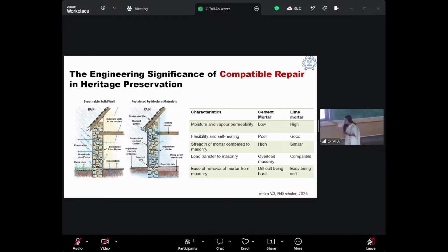When you are sealing it with a cement plaster now to make it repaired or to make it new, you are sealing all this water, vapor movement, salt, everything inside. So pressure starts building up. Crystals will grow, it will exert stress. What happens when stress builds up inside? It bursts one day. In structures, it doesn't burst like us, but when pressure builds up, cracks form in those portions and cracks extend and then failure happens. And that new layer that you added will come out along with some of the heritage material, which is stone. This is why cement is asked not to be used in heritage structures anymore.